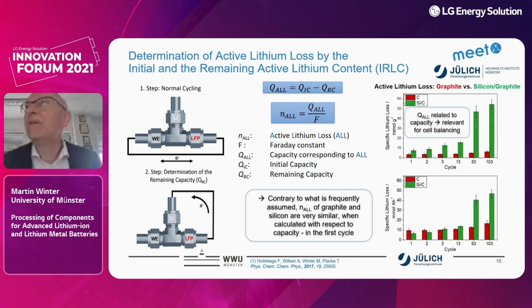If we look here at the active lithium loss of graphite against silicon graphite, determined by the IRLC method, we see two graphs. One where we look at the specific lithium loss in millimole per gram. This is always interesting because we are looking at our capacities in ampere hour per gram, for example, or also our energies in watt hour per gram. But what is more meaningful in a full cell is the specific lithium loss in millimole per ampere hour. So the lithium loss normalized to the capacity, because at the end, in this full cell, you're not balancing the capacities by a kilogram of material, you're balancing the capacities by ampere hour of material.